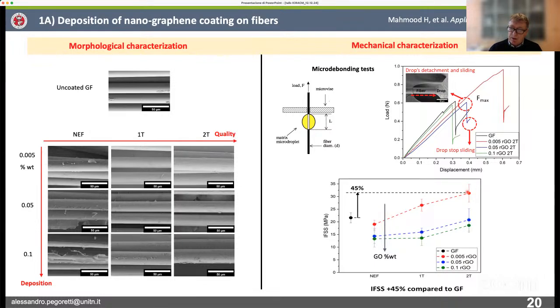By optimizing the conditions, it is possible to increase the adhesion over the initial one by a factor of 0.5 roughly, so roughly 50%. And this is basically how we can improve the adhesion in a relatively easy way.